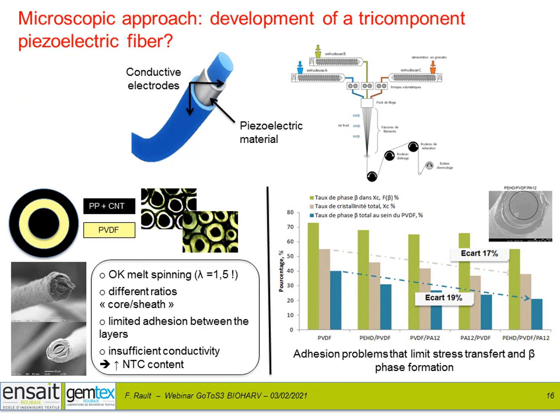In terms of the microscopic approach, we have carried out various studies using a three-component melt spinning pilot. We have studied different polymers to obtain the electrodes around the PVDF core layer. The major problem remains the adhesion between the different layers, which limits the transfer of stresses. This has the effect of limiting the drawing ratio and also the beta phase content of the PVDF layer. The addition of conductive fillers also has an impact on the process and final properties.